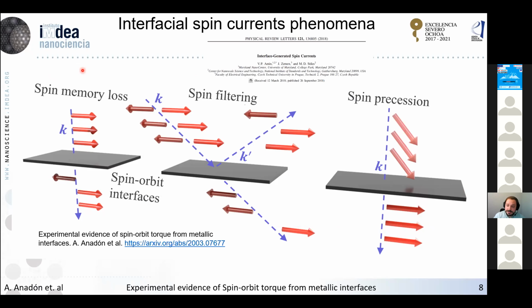And the first one is the spin memory loss. Spin memory loss is a decoherence effect. When you apply a spin current in the perpendicular direction to a spin orbit interface, the spin current loses part of its coherence. You basically lose part of the polarization of this spin current. But also, as I said, when you apply an electric current in the in-plane direction, you can have phenomena such as spin filtering or spin precession. And spin filtering happens when currents with parallel and anti-parallel directions have different scattering amplitudes when they transmit or reflect at the interface, and this gives rise to spin currents. In the case of spin precession, what we have is that when electrons experience an interfacial spin orbit field, they change their polarization, basically. And both these phenomena are able to generate spin currents from spin orbit fields at the interface.